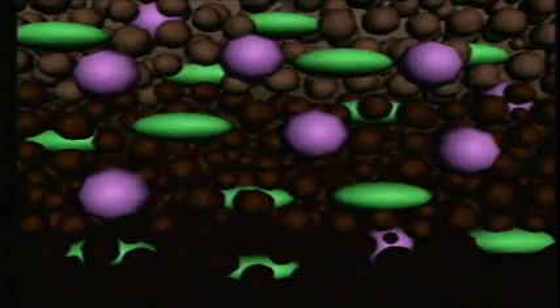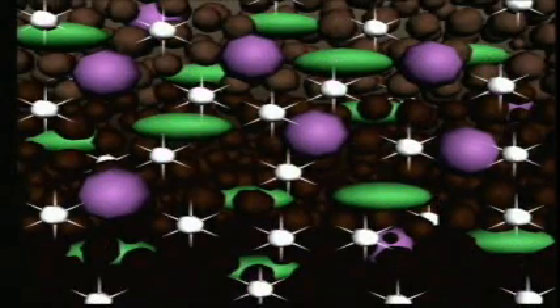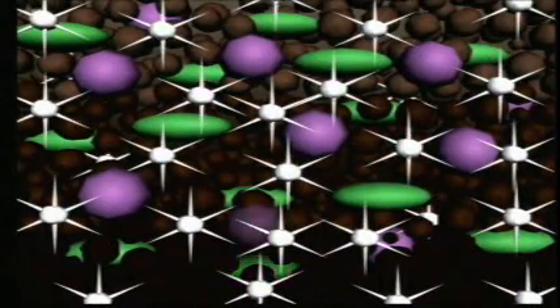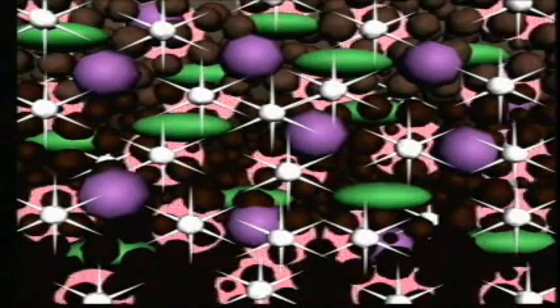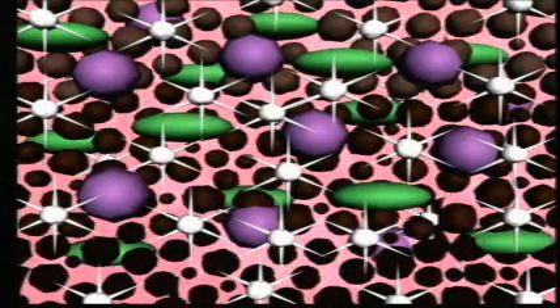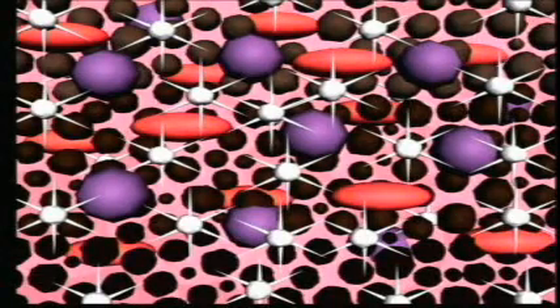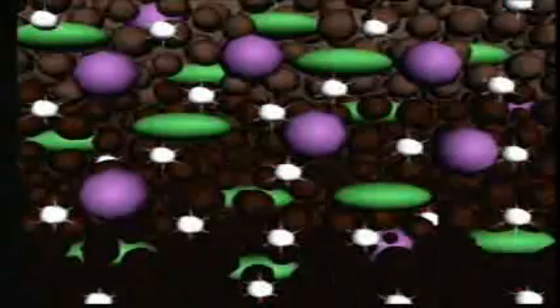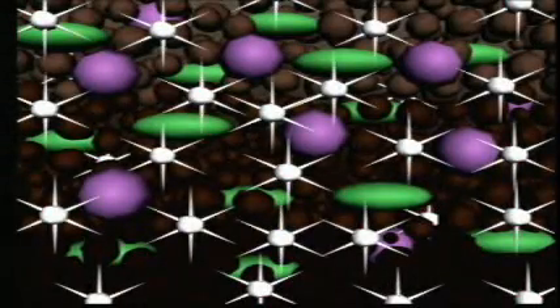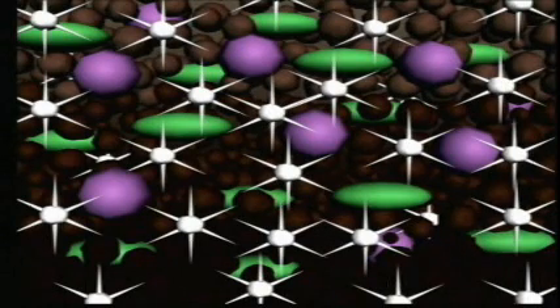Stabilization describes chemical changes to the hazardous constituents. Cement added to the contaminated soil begins to hydrate, producing calcium hydroxide. This increases the pH of the material. Calcium hydroxide in the pore water reacts with some of the contaminants, converting them to a less soluble compound. Reactions involving cement and water also produce carbonate and silicate compounds. Some contaminants present in the waste become incorporated into these compounds, forming insoluble carbonate and silicate compounds. This further reduces the leachability of the contaminants.